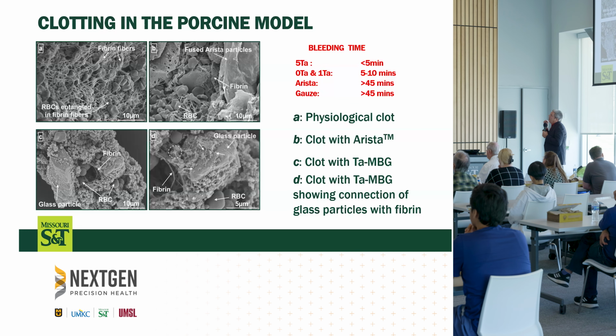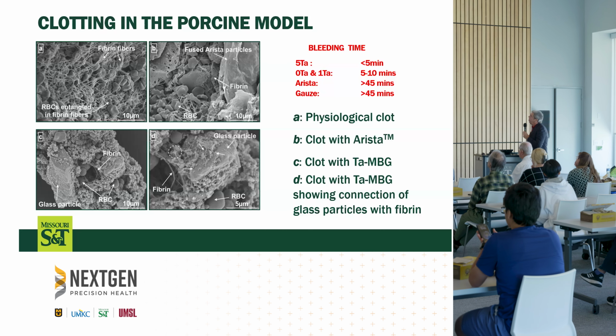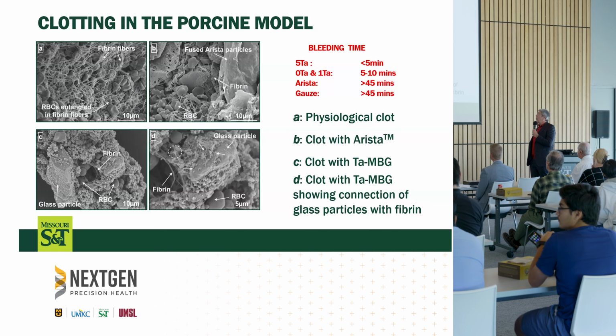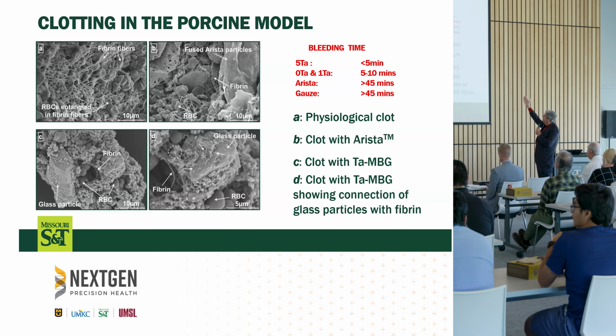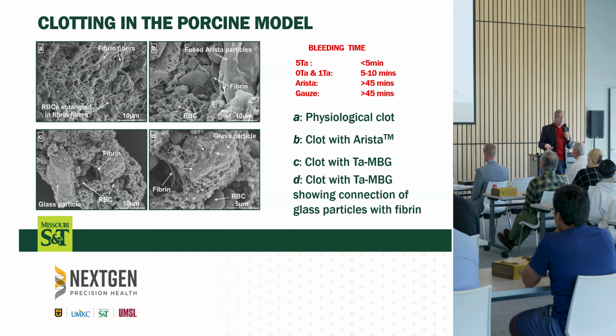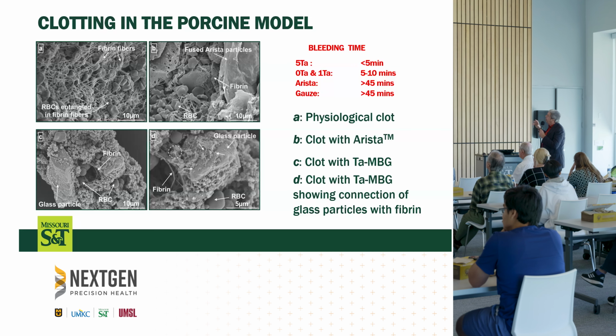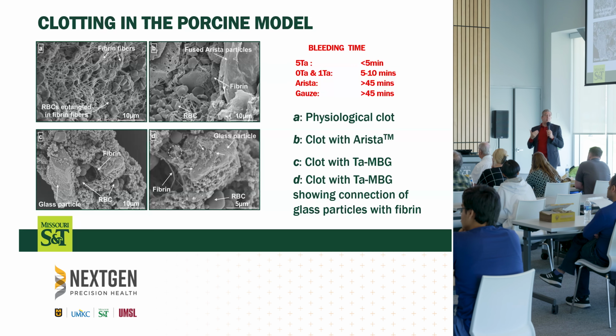When we added our tantalum-free glass, or a small amount of tantalum, we reduced that bleeding down time to somewhere between 5 and 10 minutes. But when you then added more tantalum, remember that tantalum is the big domino, it helps knock that big domino over to cause the clot, we saw that the bleeding time reduced to less than 5 minutes. If a pig's allowed to bleed for 45 minutes, or even 10 minutes, it's pretty much game over for the pig. If we can stop the pig bleeding in less than 5, the pig has a survivable chance.